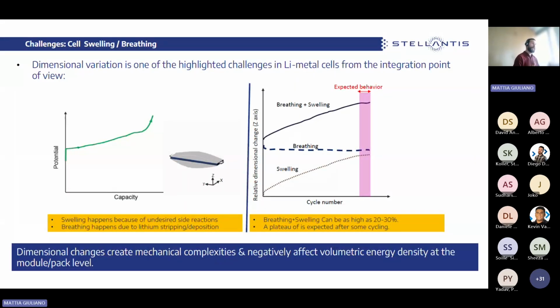Another important trend from the integration at automotive scale of solid-state batteries is related to the dimension variation of the cell, because we have the swelling of the cell, which happens in the first step of cell life due to the undesired side reactions in the very first cycle. But we have also the breathing, which happens due to the stripping and deposition of the lithium during charge and discharge. This breathing and swelling can change the cell dimension by around 20-30% of the total volume. This behavior reaches a plateau after some cycling, but this dimensional change creates mechanical complexities during the integration at pack level, and can negatively affect the volumetric energy density at module and pack level.